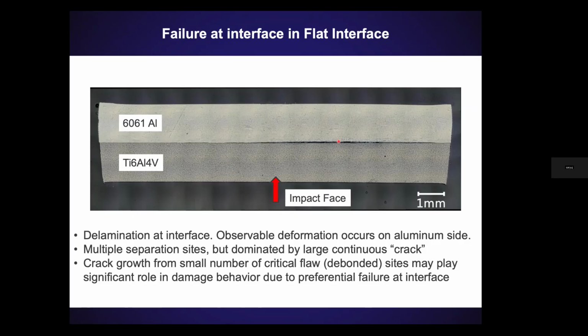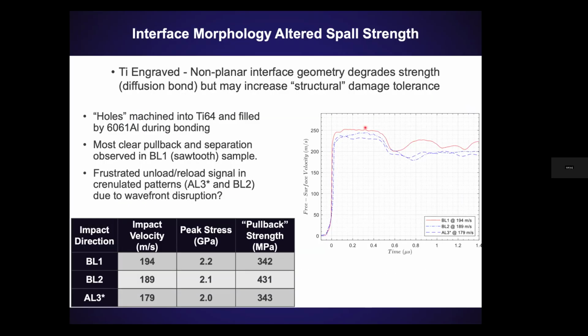There would be delamination of the interface rather than that void nucleation and failure that we were seeing in aluminum in the MD simulations. Well, that's kind of concerning. In fact, and I'll discuss some reasons we think that's happening, when we go to the other interfaces and we measure spall properties, like this pullback strength, we see that the strength is very similar on all of these interfaces.